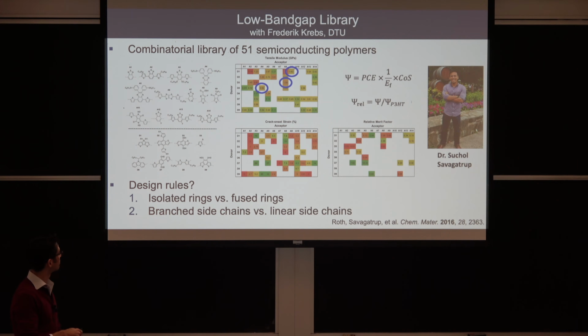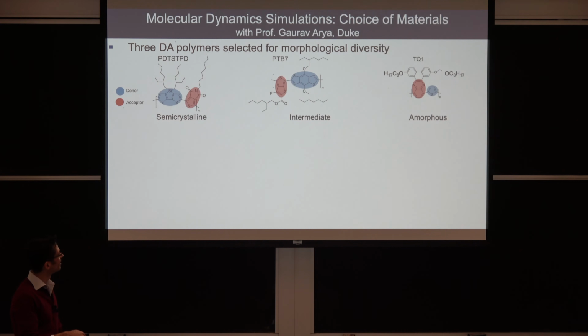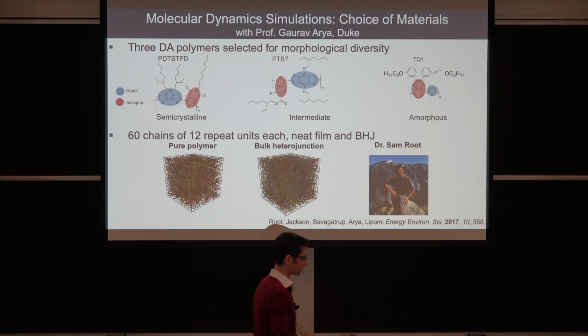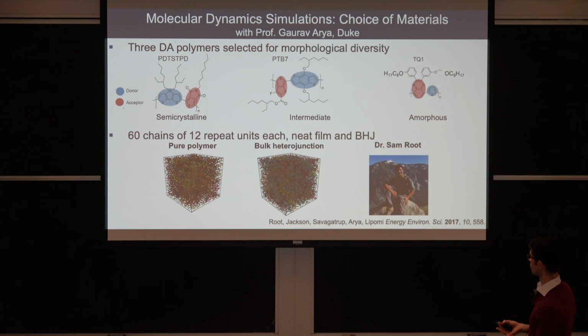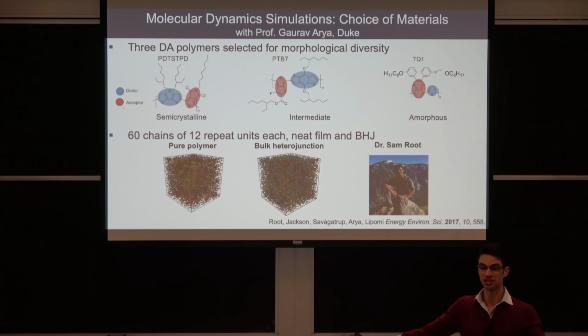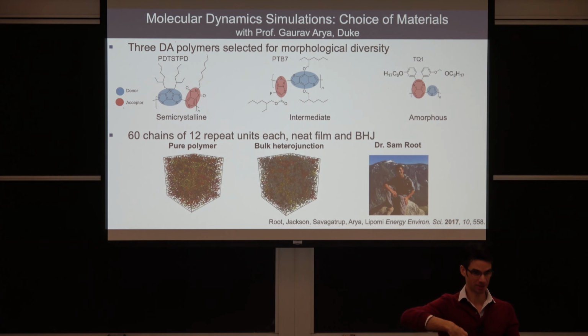And those we chose because a lot is known about them, and also because they form this wide range of microstructures. So from semicrystalline, PDTSTPD, it took me a long time to practice saying that, PDTSTPD, anyway, PTB7 and TQ1 are semicrystalline, intermediate, and amorphous. So my student Sam Root, who's now a postdoc at Harvard, actually working for my old PhD advisor, did these molecular dynamics simulations in which he calculated the properties of 60 chains of 12 repeat units each in both the neat film, that is the pure film of the polymer, and the BHJ, which is the bulk heterojunction, which is the polymer mixed with the fullerene as the electron acceptor for a solar cell.